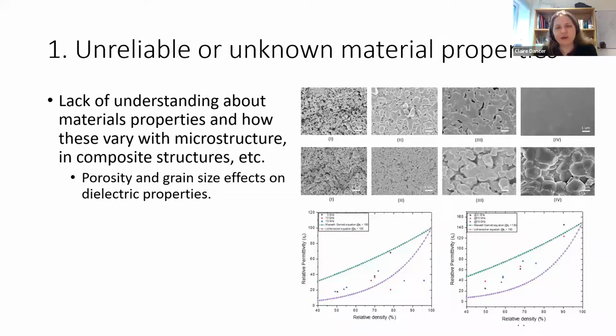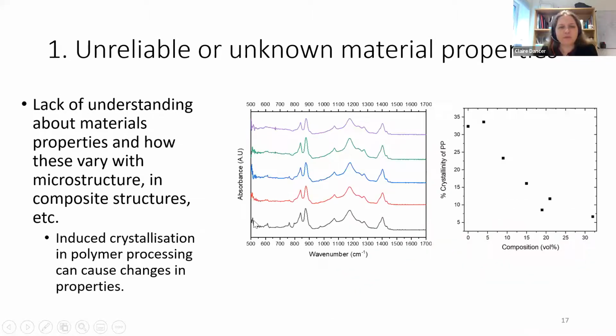A manufacturer might hand you a data sheet, but then you're confined to buying something from them, not to making what you need. But we know from the measurements we've done in the group that you change the porosity of a material and you're going to get quite significant differences. So what that means in practice is if you have to change your process temperature and therefore you affect your ceramic microstructure, you're going to see quite a radical difference in the dielectric properties. We could be talking about going from 20 here to more like 100 in the permittivity of these materials, and that's quite a significant effect. So that's the first one.